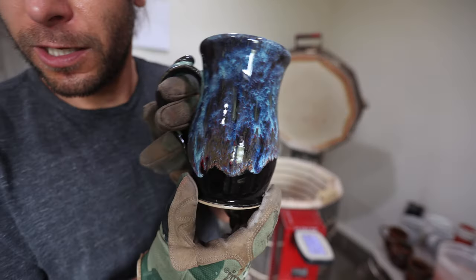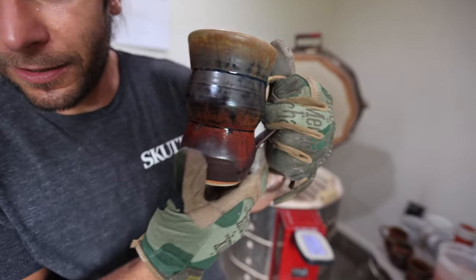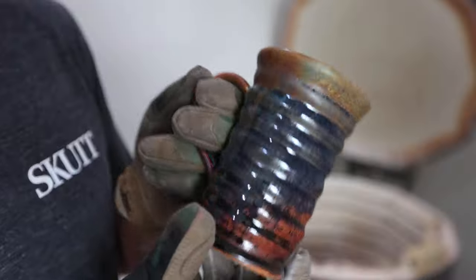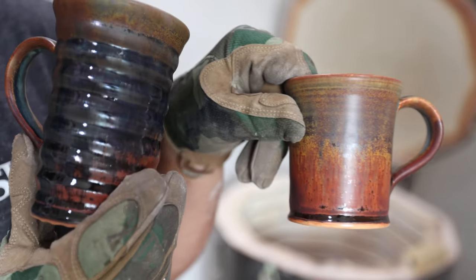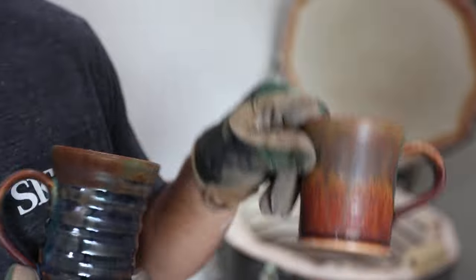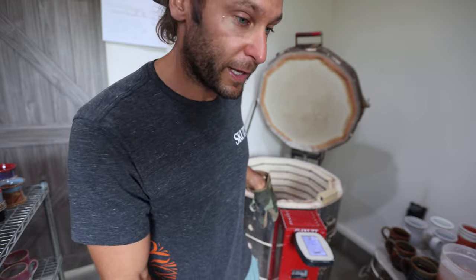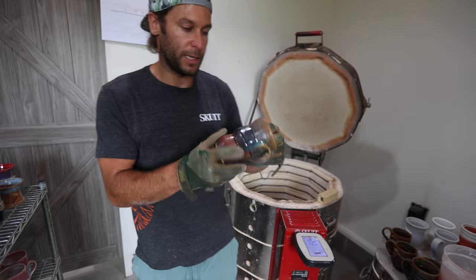Got some gorgeous northern lights with red — really good. Got a little bit of drippage going on there but we'll grind that off. This glaze seems to go back and forth between getting really glossy — this is the same glaze in the same kiln applied the same way, just on different shelves. This piece was on the bottom shelf and this one was on more of the top shelf — isn't that interesting? The thermometer says 130 in this kiln area but 90 over in the other area.